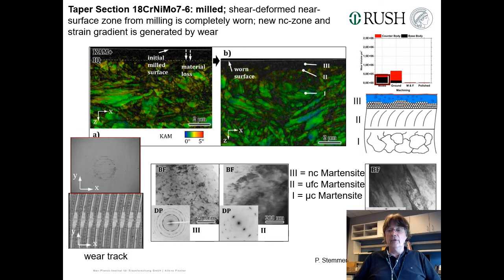While the base material, this is area one here, is microcrystalline, the strain gradient here is deformed microcrystalline material with a lot of defects, and the tribological material up here is nanocrystalline. So it is more or less the same structure as we have seen for the FCC materials, but now in these applications, sometimes you only have 2 micrometers, 1 micrometer, or half a micrometer for this entire picture here.